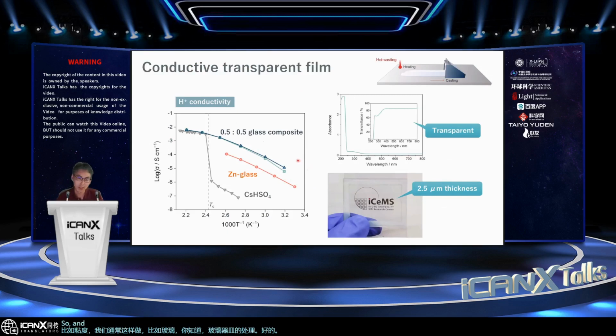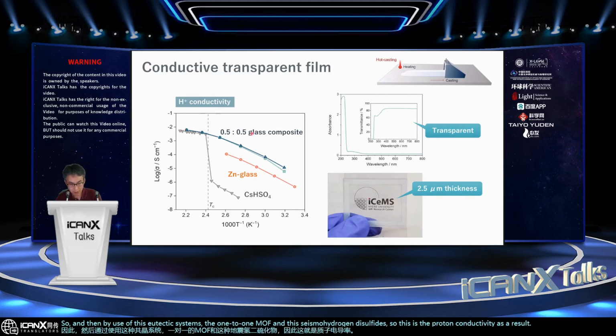So by use of these eutectic systems, the 1-to-1 MOF and cesium hydrogen sulfate, this is the proton conductivity as a result. With use of these two benefits, we can get a very high proton conductivity in a wide temperature regime, which is much higher than the parent MOF glass and the pristine cesium hydrogen sulfate.